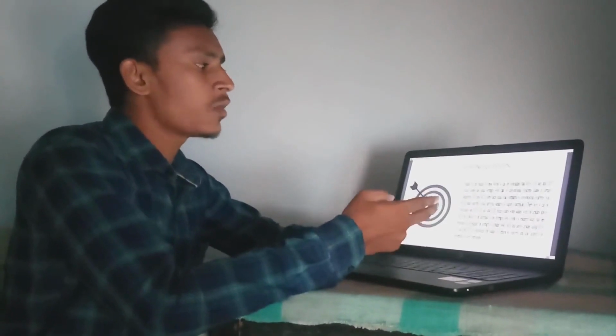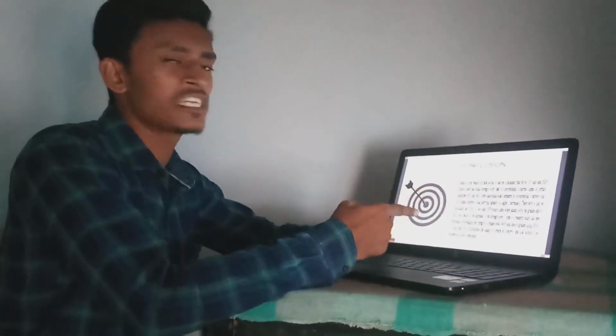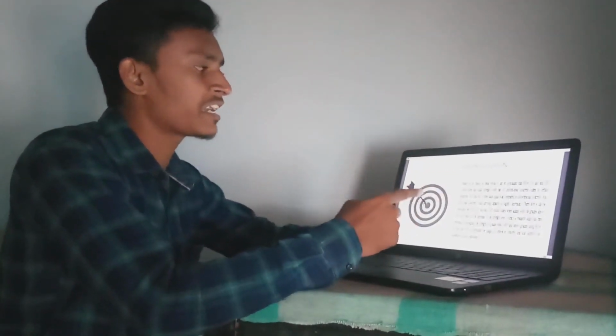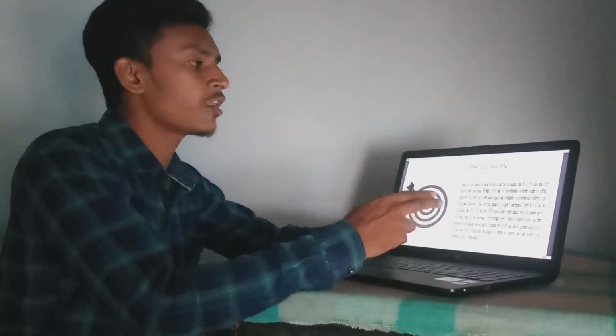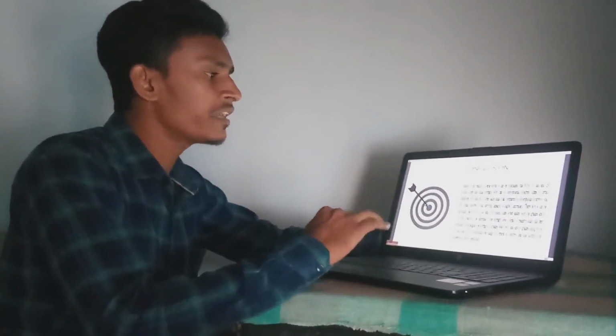And coming to the conclusion, based on the results of this work, it can be concluded that RHA, fly ash and ESP mixed cubes attain strengths equal to those of conventional concrete cubes in certain categories. M20 and M25 cubes take equal load compared to conventional concrete, and the load carrying capacity of M30 grade concrete cubes is slightly decreased.